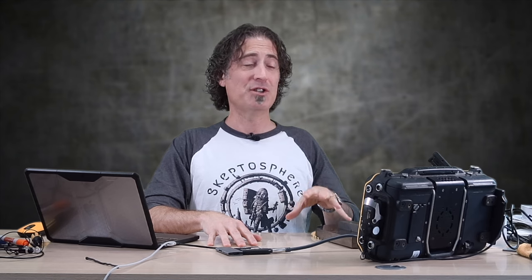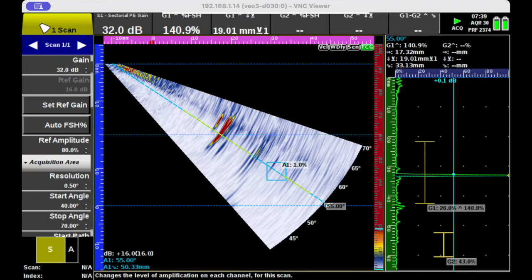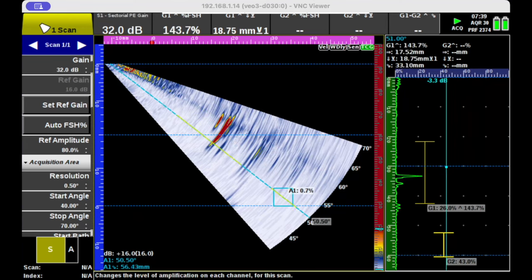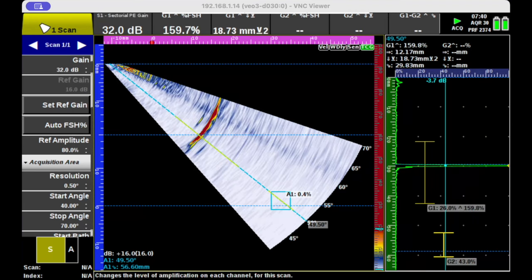Another interesting thing is that because of this effect, you can actually reverse engineer a calibration to tell whether it was done on a hole or a notch. If you take the signal and just have the probe in the air — you don't even have to have it on the block — turn the gain way up or adjust the palette. What you'll see is, if it's done on a notch, you'll see this huge boost on the upper part of the S-scan, kicking in right around 60 degrees. I think it's really important to understand the limitations of the physics that we're applying when we do ultrasonic testing. A good understanding of what mode conversion is and what effects it's going to have on your screen is really important.